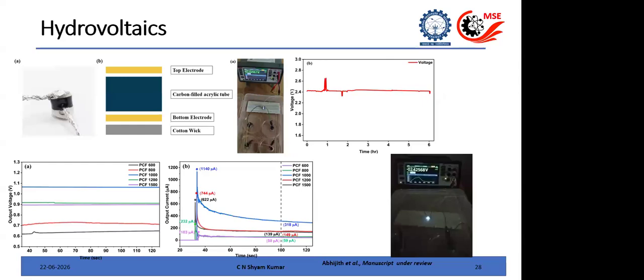Now, this is mainly because of two things, I would say. As we increase the graphitic content, the conductivity will definitely increase. But when you increase the graphitic content, after some time the porosity will come down because of the formation of these highly graphitic layers. The porous nature of the carbon comes down drastically, which you can see from the BET. And the second thing is that as it becomes more graphitic, the functional groups in the carbon come down.